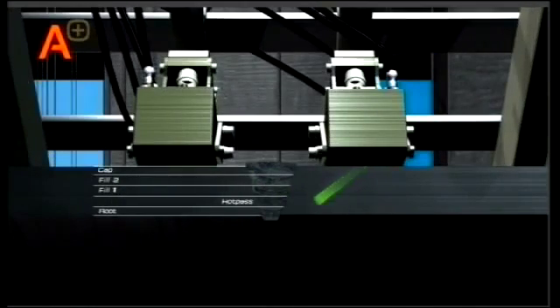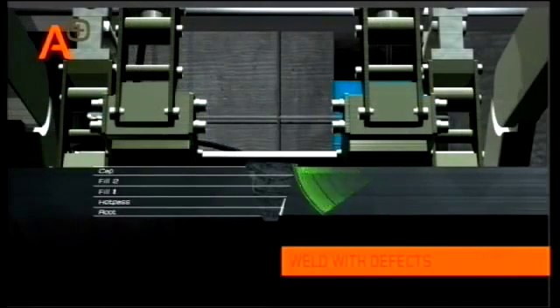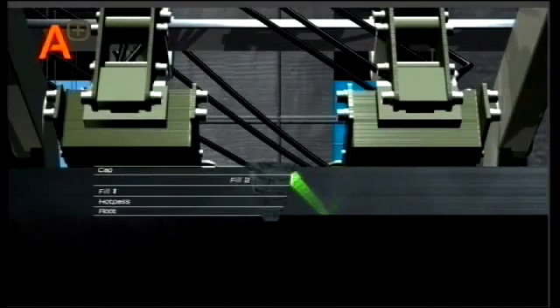Whenever there are no welding defects present, the ultrasound waves are not reflected and disappear into the pipe wall. There is no sign of welding imperfections. If welding imperfections are present in the weld material, typically due to so-called lack of fusion, a part of the sound beam emitted is reflected and detected by the receiver element of the transducer. Depending on the inspection type, the emitter and receiver can be in the same housing.